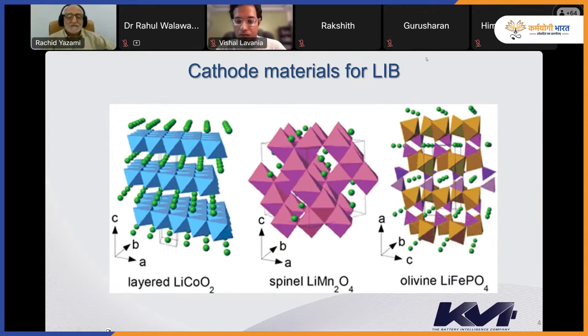Okay, so this slide shows the crystal structure, the schematics, of the most common cathode materials. On the left hand side, we have the layered lithium cobalt oxide, but you can replace cobalt with nickel, manganese, and cobalt, what we call NMC. So the structure is the same. You have metal oxide slabs in the blue color, and between the slabs, or layers, lithium ions in the green color occupy the octahedral sites in this structure.